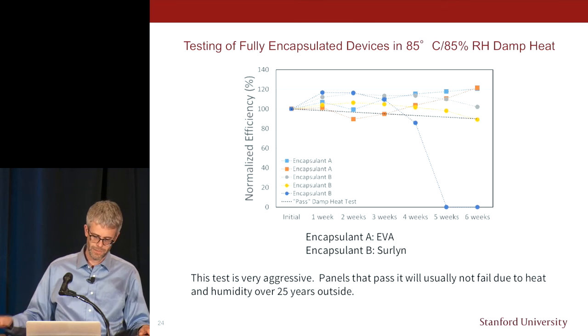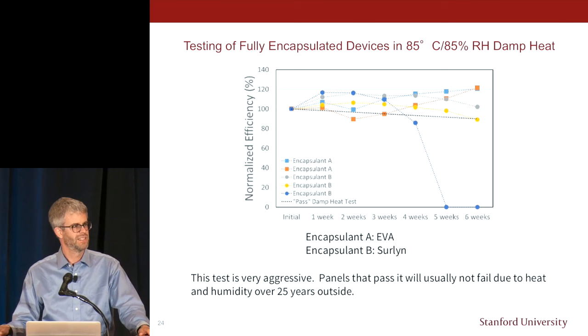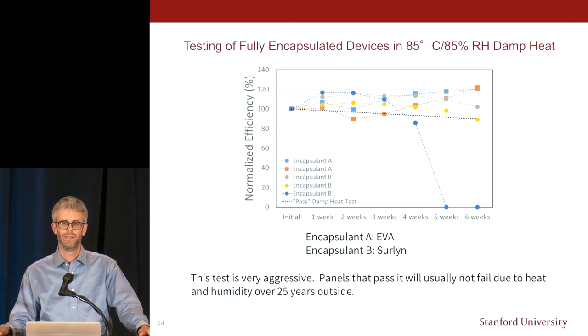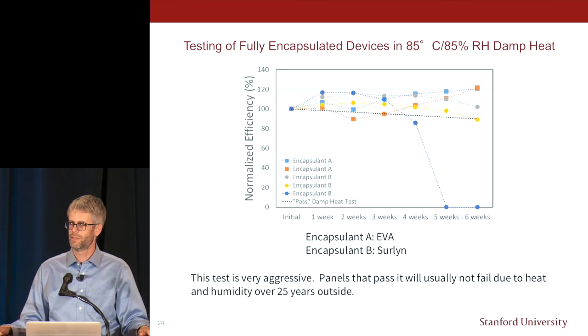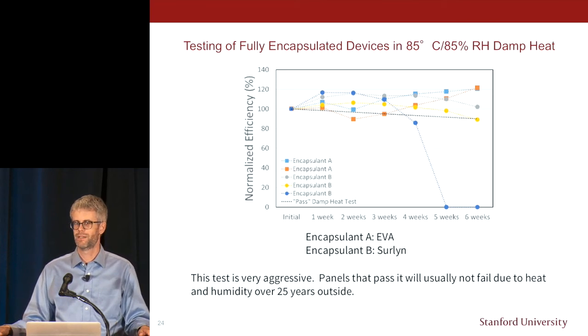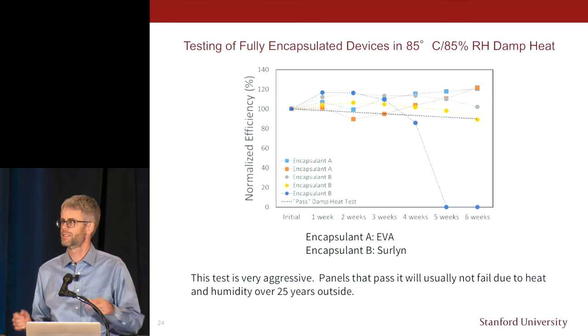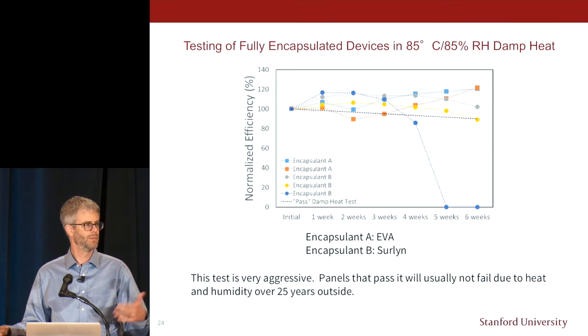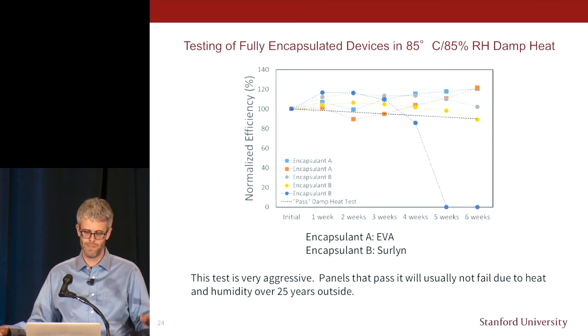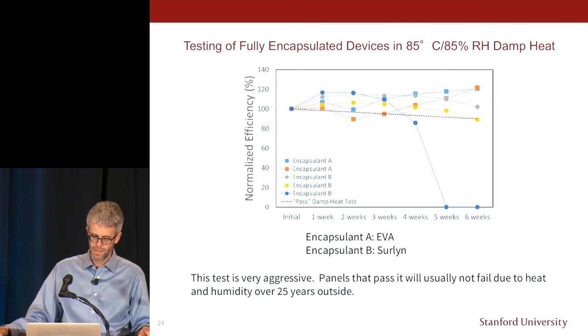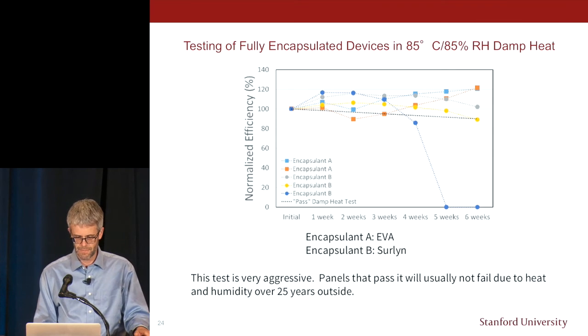In fact, if you look closely at the data, the efficiency actually went up. Previously, we couldn't anneal our cells because they were so thermally unstable, and now we're able to anneal them and even improve the efficiencies. So we're really excited about that.